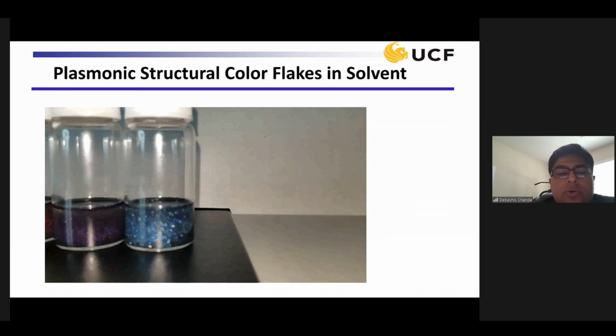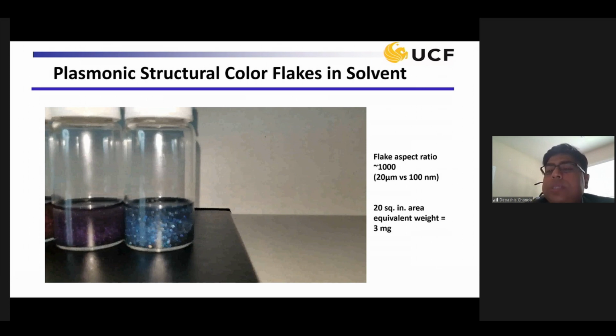That shows that we could actually create enough quantity. Two points I want to emphasize and then show some nice cool applications based on them. One is the aspect ratio. These structures are only about 100 nanometer thick, but laterally they are 20 microns. So that is an aspect ratio of about 1,000. So they're ultra light. Because of this extremely high aspect ratio, it allows us to cover a very large area. With 3 milligrams of weight, we could cover, say, 20 square inches, which is an extremely large area.